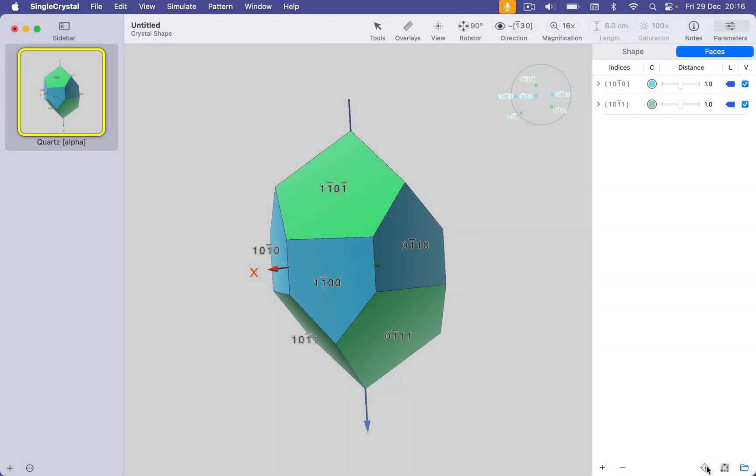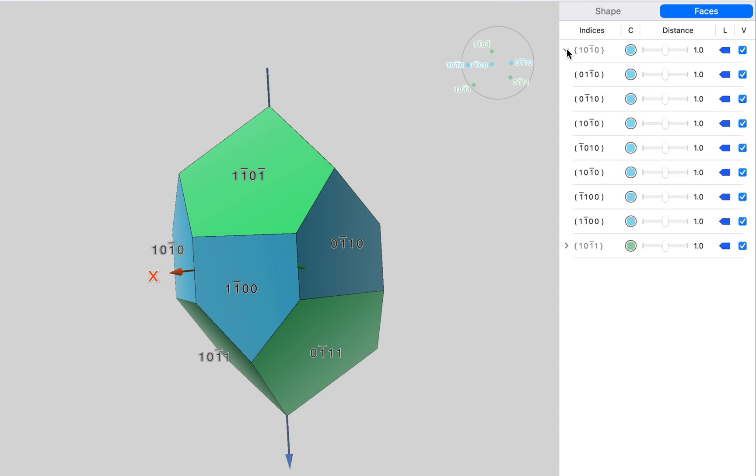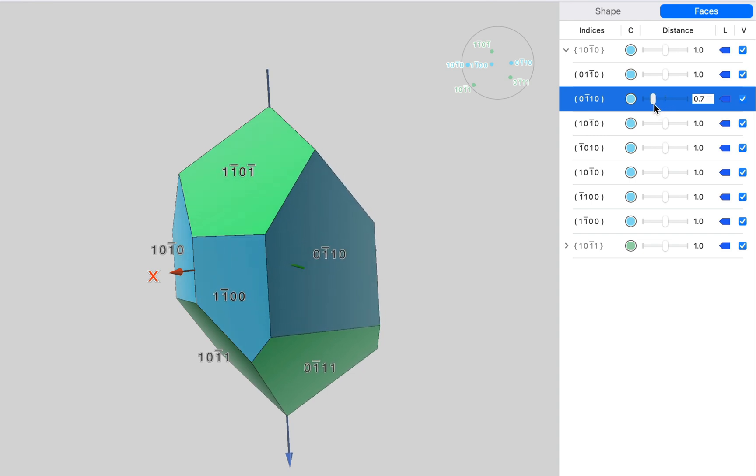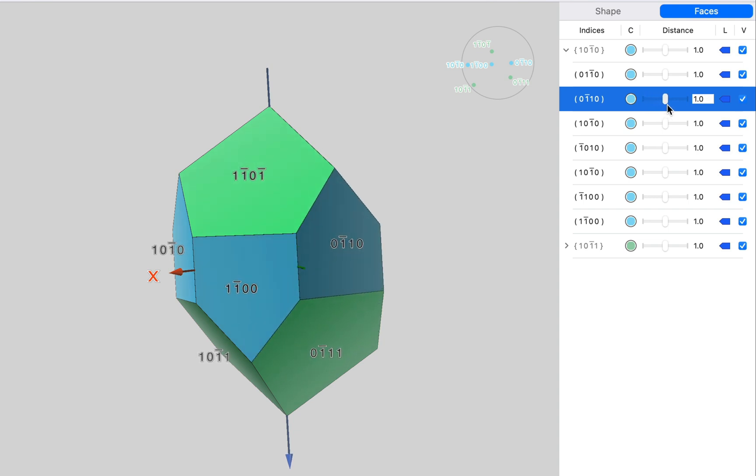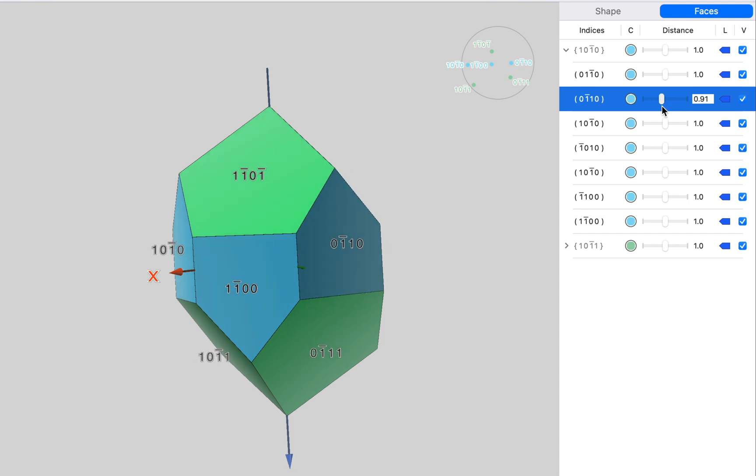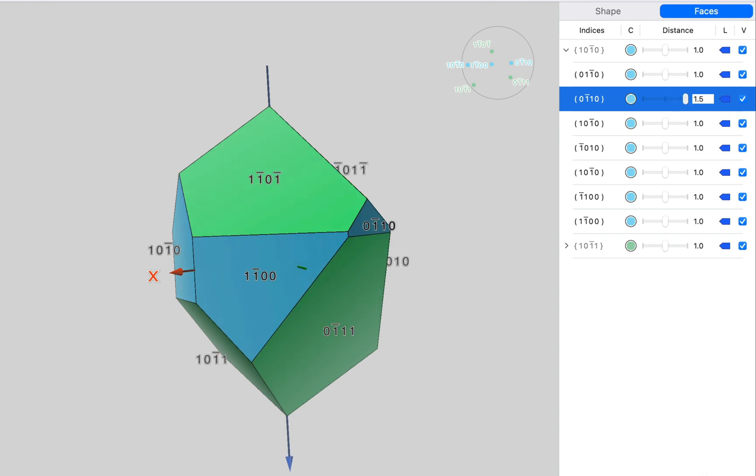The next thing we need to do is to set the relative sizes of these faces. And we do this by specifying their distance to the centre of the crystal. This is sometimes referred to as a Wulff construction. But there's really nothing clever about it. The distance of the plane to the centre of the crystal defines its relative size. And that has some relationship to the stability of the face. So let's have a look at the 10-10 group of faces. And let's take one of these faces and change the distance. Let's move it closer to the centre of the crystal. And you can see it gets bigger. Further away, and it gets smaller.